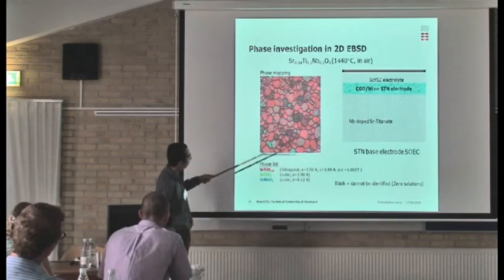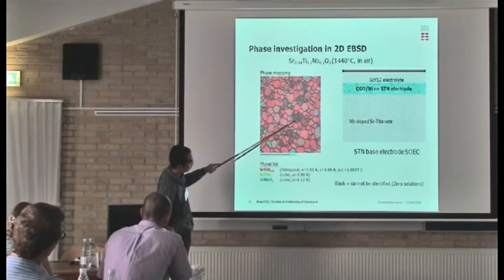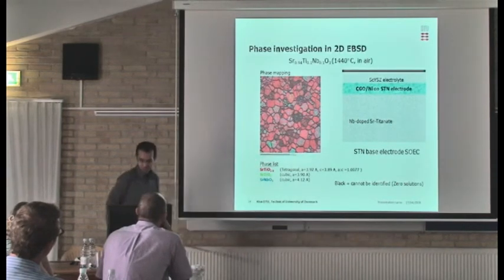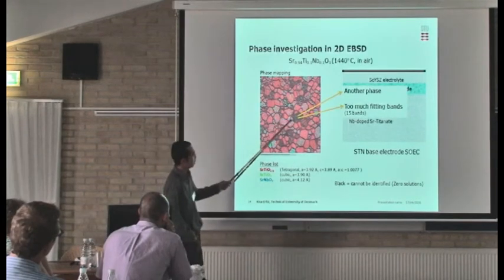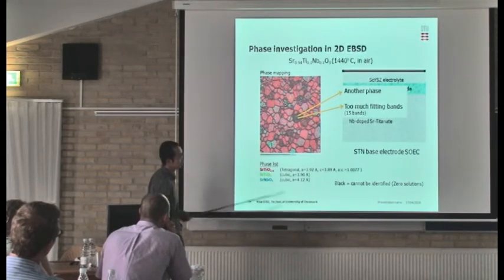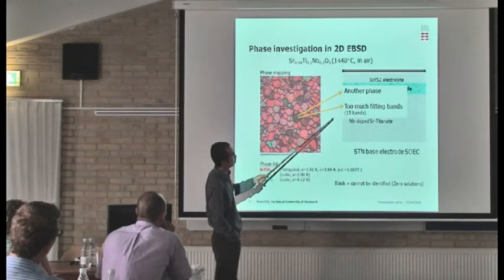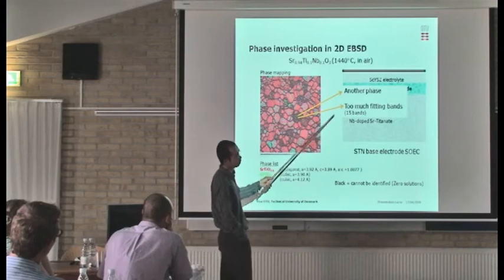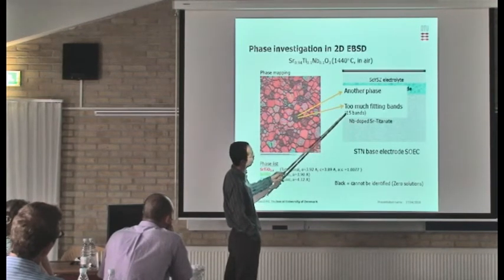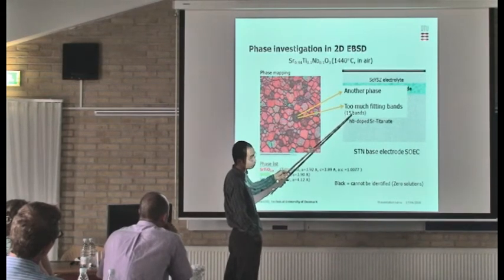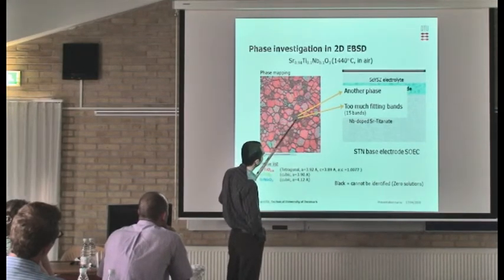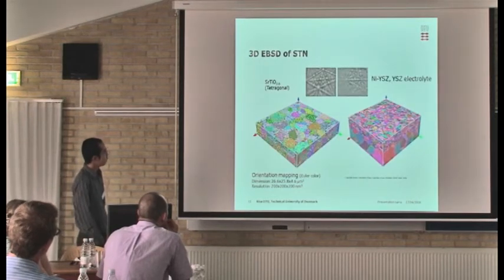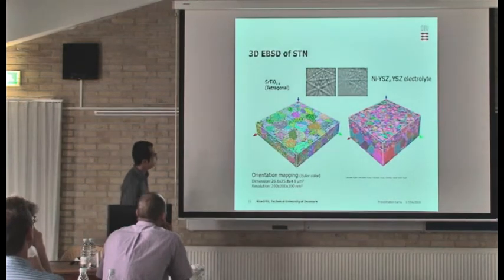Another thing I can see is this gray — black and gray. Black means an unidentified phase, or zero solution. It could also be another phase that our database has. I used fifteen bands to do this mapping; normally seven bands are used. More bands gives more accuracy but also more zero solutions, so that could be the reason why this area is black.